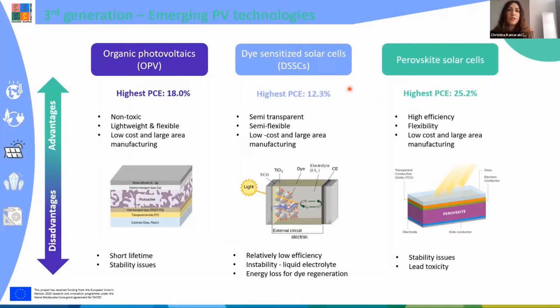Then we have the dye-sensitized solar cells. These types of solar cells are quite, let's say, strange because they are photochemical solar cells. As you can see here, we don't have a single layer of absorber, but we have small dye molecules. These molecules are actually absorbing the light and generating the carriers. However, the generation of the carriers leads to the oxidation of the dye. So a liquid electrolyte is needed in order to regenerate the dye and bring it back to its original state. The presence of the liquid electrolyte is a drawback because it induces long-term instability in the solar cell. And also the fact that we need to regenerate the dye costs us some energy. So that's why we have lower efficiencies, up to 12%.